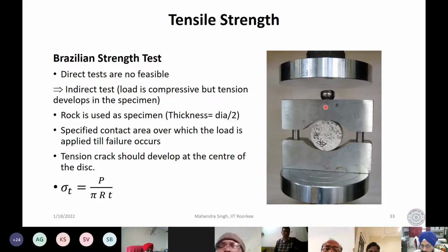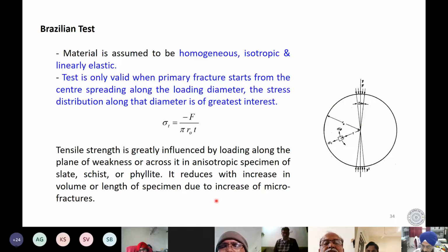So what is going to happen when you apply load? There is some standard area in contact with the steel platens, the steel jaws, and when the load is applied, tensile stress is going to develop in this direction, and the specimen is going to fail. We have to observe very carefully that the crack starts developing at the center. If it is not developing at the center, if it is chipping here, then we have to discard this test. And then equations are available using which one can find out the tensile strength.